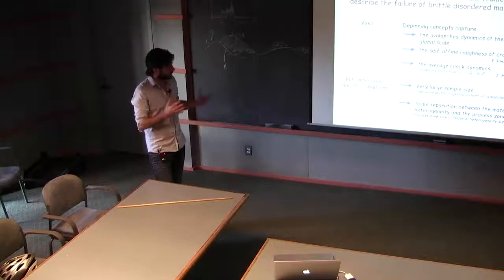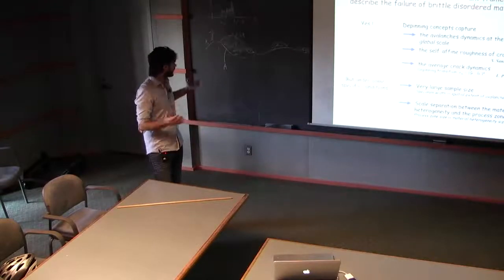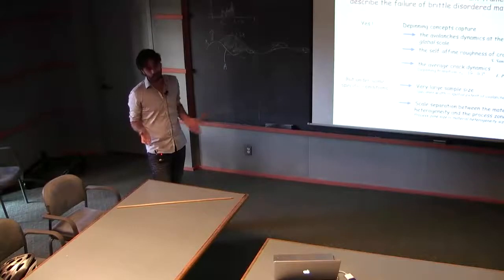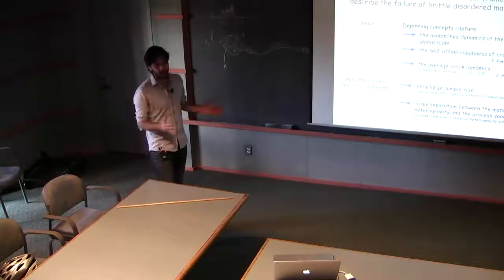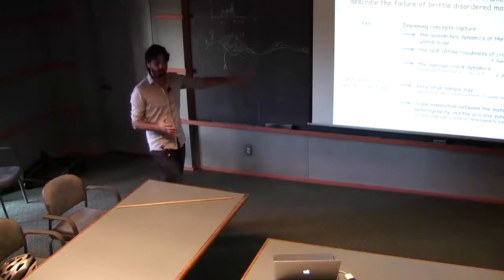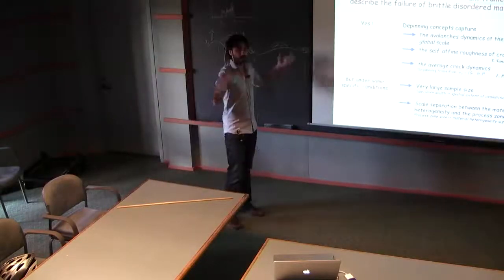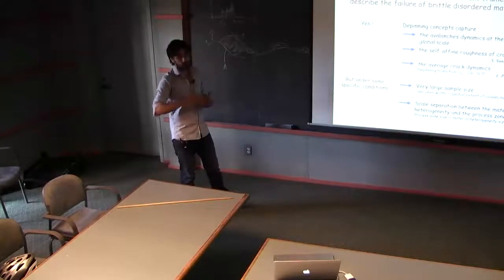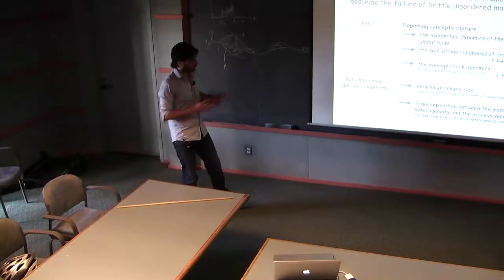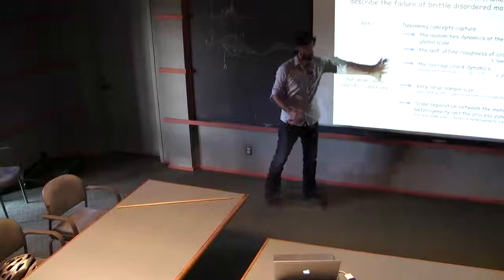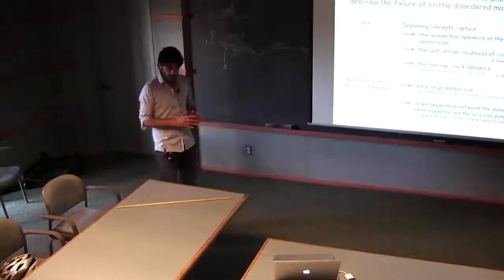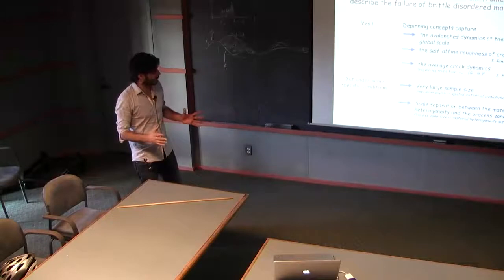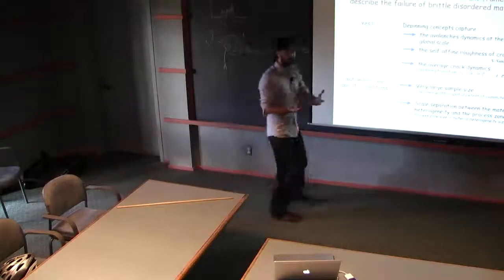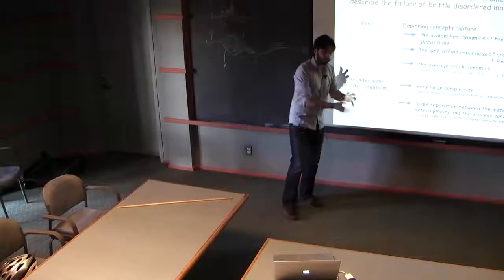Is that the cutoff size of these avalanches, the maximum size of this fluctuation, is bounded by the system size. Especially when we talk about brittle fracture, there is no length scale between the heterogeneity size and the system size. So that's why I have all these power law distributed objects. So the larger your system is, the larger the fluctuation will be. In some cases there is not always crackling, but when you have crackling, it's not easy to define a representative volume where you can put this fluctuation in and then smooth them out. I would say this is like the earthquake problem.